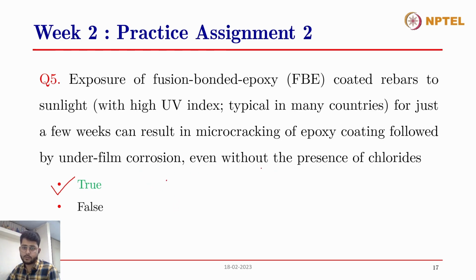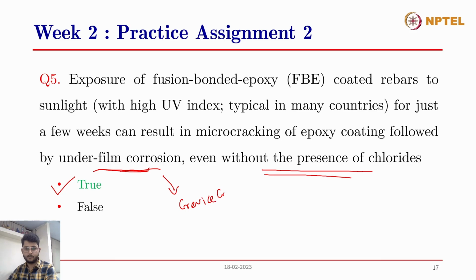And even if there is no presence of chlorides, then also we had last time discussed about the crevice kind of corrosion. Due to the non-uniformity over the surface, these anodic and cathodic sites will be produced on the steel surface, and that will promote the crevice kind of corrosion, which will deepen at that particular location. So this is the underfilm corrosion. Even if there is an epoxy coating, but if it has surface micro cracks, then it will accelerate the corrosion process even without the presence of chlorides. So this is a true statement. And this under film corrosion is the crevice corrosion.